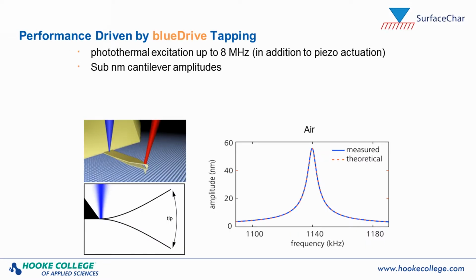Another feature that they've integrated into this large sample instrument is how we drive the cantilever. Driving the cantilever means that we shake it so that it's oscillating, typically at a resonance frequency, so that we can image in modes called tapping mode, for example. Typically we have a piezo underneath the cantilever that shakes it, and that piezo actuation is what we've all been doing for 30 years. This technique is a different drive, using a blue laser here to drive the cantilever instead of that piezo.